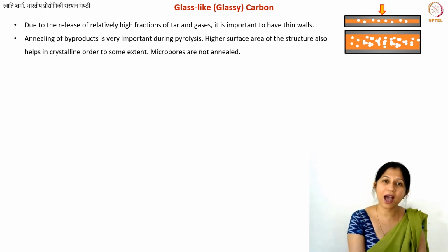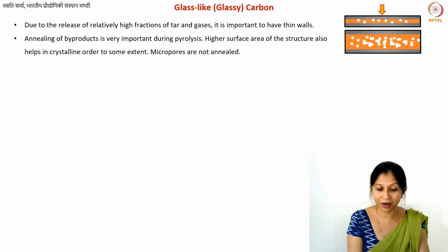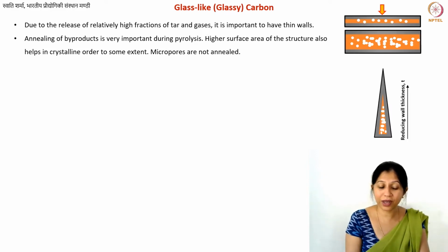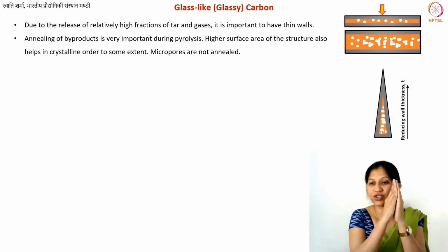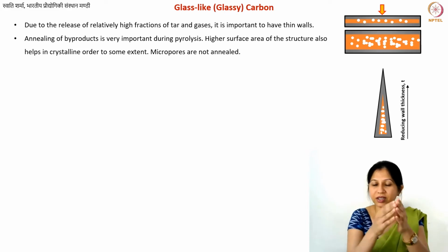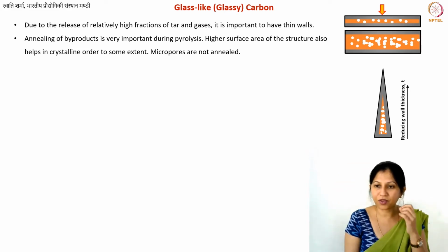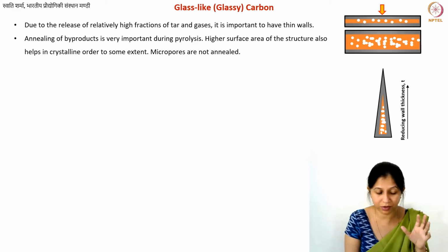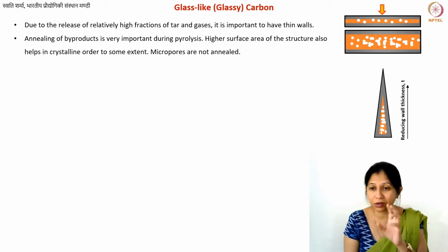Okay, so if you want to decide what is the optimum size of your structure, what is the experiment that you can perform? What you can do, and this is in fact done at industrial scale, is make a wedge. This is just the cross section of the wedge. So you have a certain depth in it, like a piece of cake or something like that. You can make this kind of structure, and then you can do the heat treatment at whatever parameters you want to use. If you want to use 2000 degrees, or you want to use 3000, whatever your condition is.